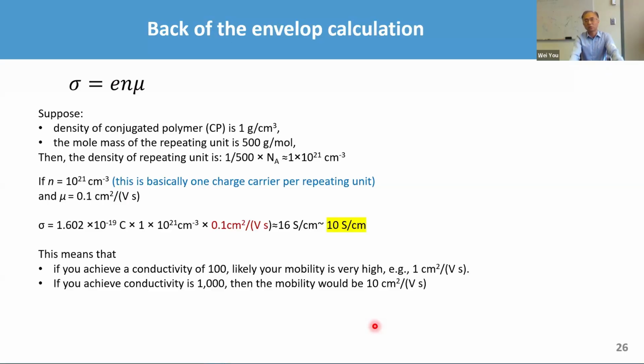So let's take a quick calculation. Suppose the density of a conjugated polymer is roughly about water density, 1 gram per centimeter cubed. The molar mass is about 500 grams per mole. So if you do the calculation, you realize that the highest carrier density is about 10 to the 21st per centimeter cubed. That's basically saying that you have one charge carrier per repeating unit, which is very high. Assuming that you have a mobility of 0.1, then if you do the math, you realize you can only get up to 10 Siemens per centimeter.